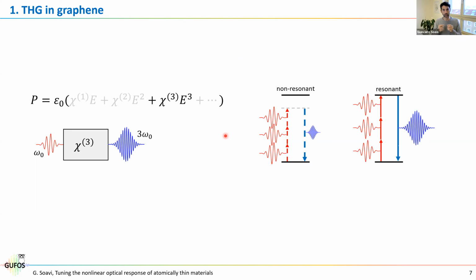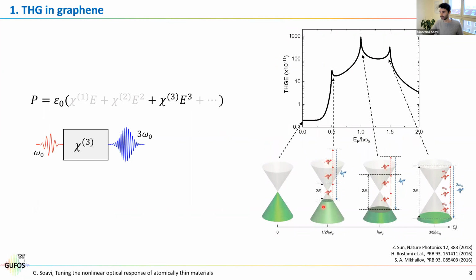So if you wanted to switch on and off, let's say, the efficiency of the process, or you want to go resonant with the material, the only thing that you can do is to change the photon energy. So the gap is fixed, and you need to tune h bar omega 0 until you are resonant with your photon energy. And this is what is special about graphene, because graphene has this peculiar linear cone, so this linear dispersion that is given by the honeycomb lattice and by the fact that you have carbon atoms in each place of this honeycomb lattice. And the other peculiar advantage of graphene is that we can now tune the gate voltage.